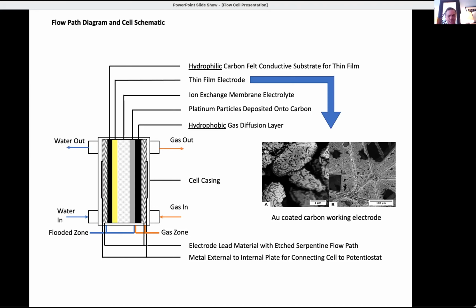And you do have to replace electrodes sometimes in these techniques, so that lowers the cost significantly. And so using RF sputter deposition techniques, we have been able to greatly decrease the gold loading used in these techniques by orders of magnitude compared to other commercially available technologies.